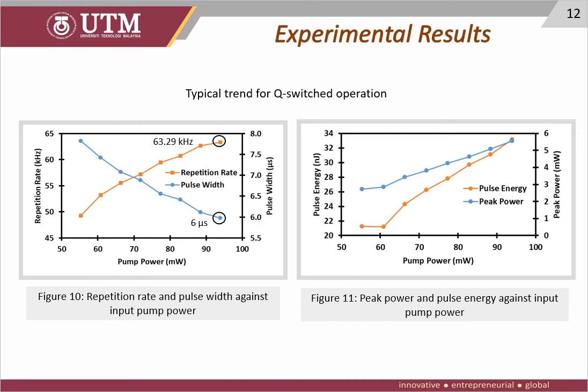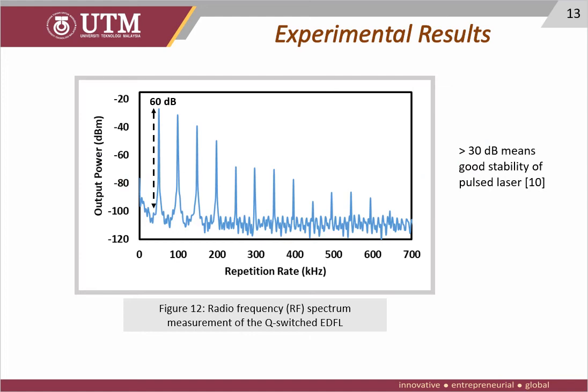Okay, this figure shows the repetition rate, pulse width, peak power, and pulse energy. So this is basically a typical trend for Q-switch operation. We got a high repetition rate of 63.29 kHz and low pulse width of 6 microseconds. And the pulse energy and peak power also show an increasing trend with increasing pump power. Next is the radio frequency spectrum analyzer, RFSA. It recorded a value of over 60 dB, which surpasses 30 dB, which indicates a good stability parameter of the pulse laser.